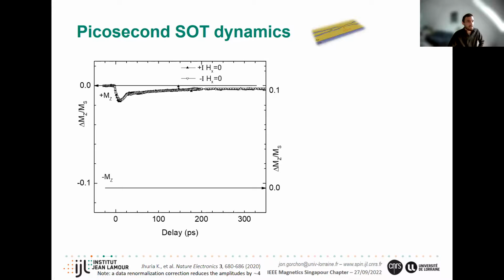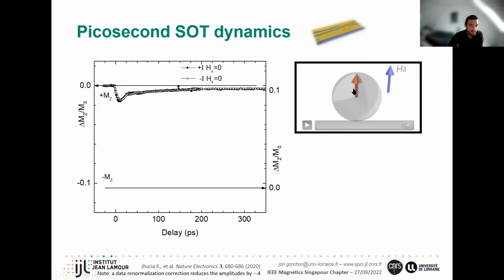So now let's look at the dynamics. We're going to be looking first at the dynamics before switching, so at low currents. What we're doing here is plotting the change in out-of-plane magnetization as a function of time. The electrical pulse is 6 picosecond wide, and it comes at 0 time delay. So we start with the magnetization pointing up, and the anisotropy field is pointing up, of course. In the first experiment there's no in-plane field, so whether it's positive or negative, the dynamics look the same.